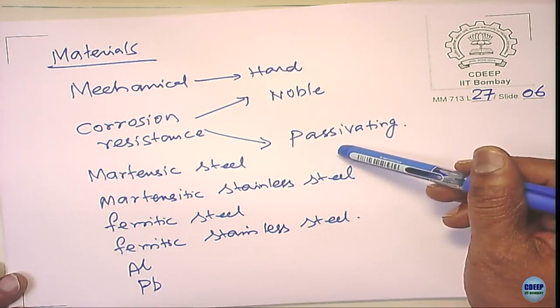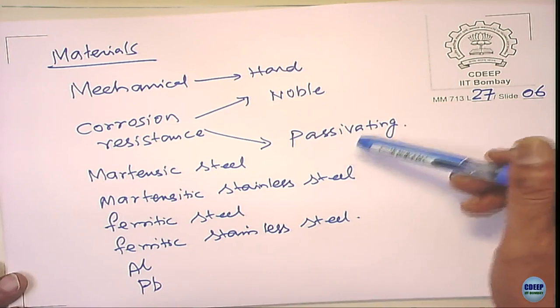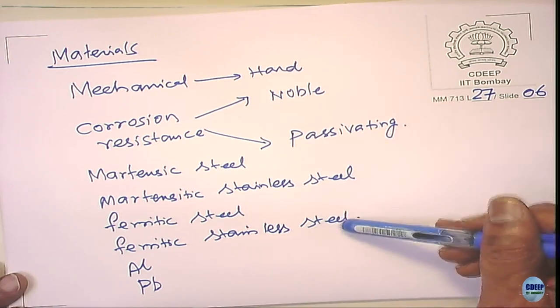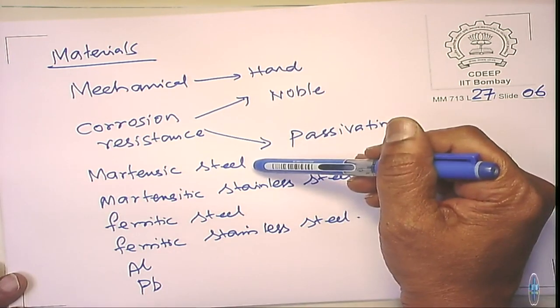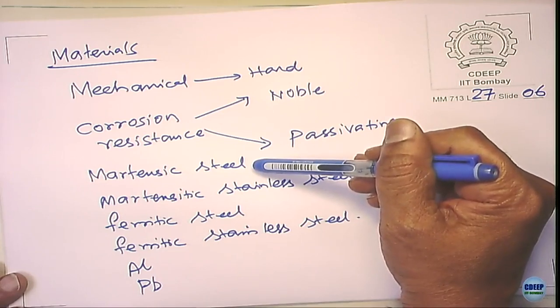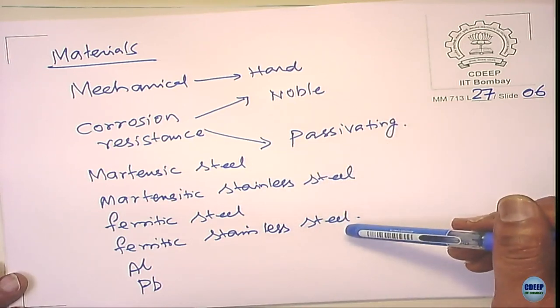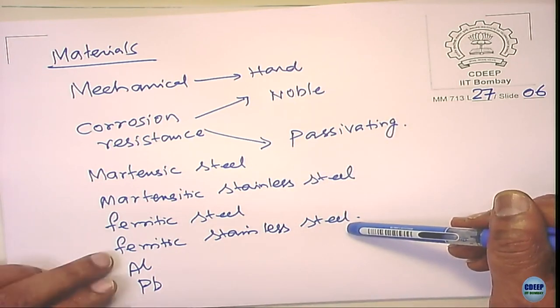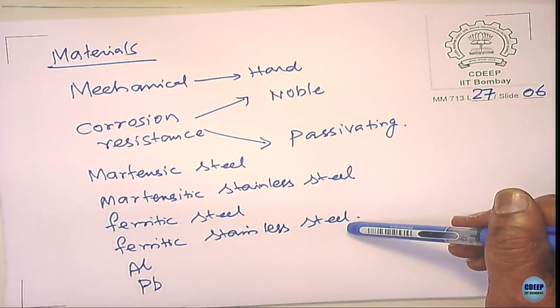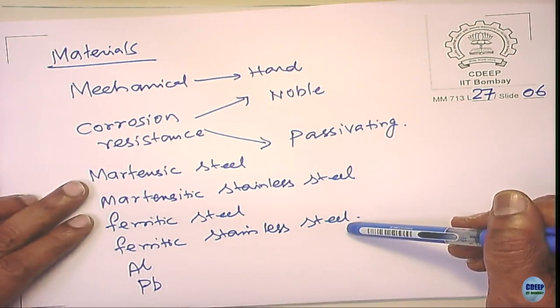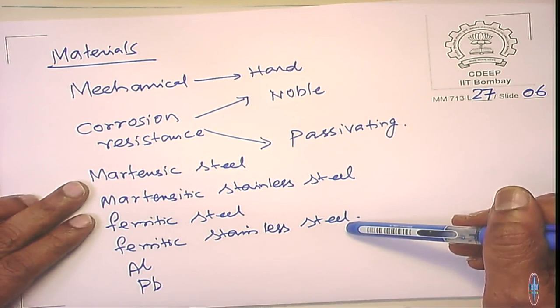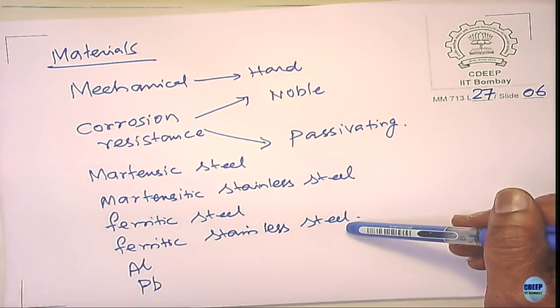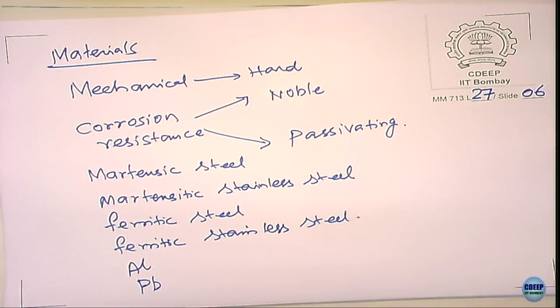In fact, it might so happen that the ferritic stainless steel may be better than even martensitic steel, depending upon the corrosive nature of the environment. If the environment is very corrosive, it is possible that the erosion corrosion resistance of a ferritic stainless steel could be better than that of a martensitic steel. Why? Because martensitic steels are generally more prone to corrosion compared to a ferritic steel.